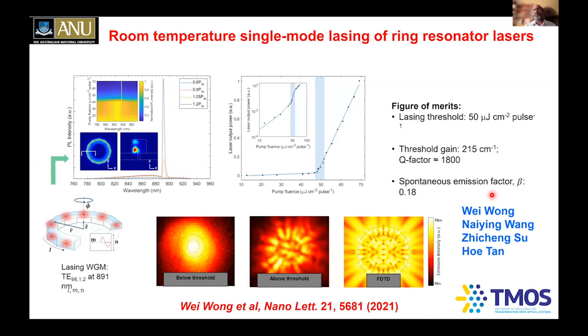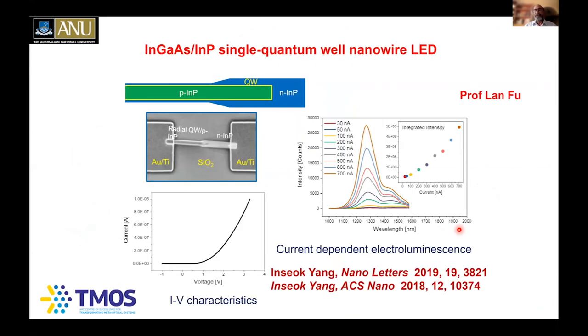So now let me move from optically pumped nanowire lasers to electrically pumped lasers. Of course, if you want to make electrically pumped devices, you need to make a PN junction, and then you need to be able to make contacts in order to inject the current into this PN junction, like a diode, for example, right? And this is the work of my former student, Dr. Inseok Yang, who is now at Samsung.